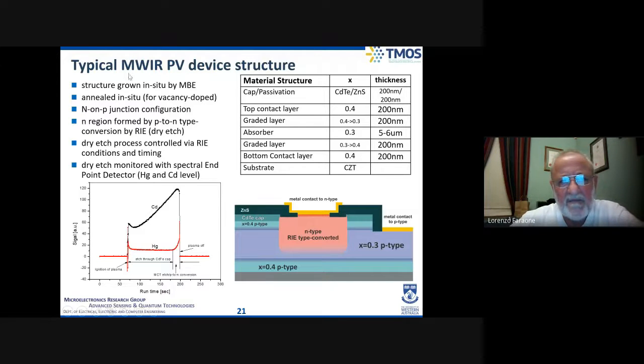I won't go into details about this typical detector structure, except to note that this is the substrate down here. We usually grow a wider band gap semiconductor, X equal 0.4, then X equal 0.3. The X equal 0.3 corresponds to the mid-wave absorber. This wider band gap is transparent to infrared photons coming in from the back - the substrate is transparent, and the X equal 0.4 layer is transparent, so photons are absorbed in this purple layer of 0.3 material.